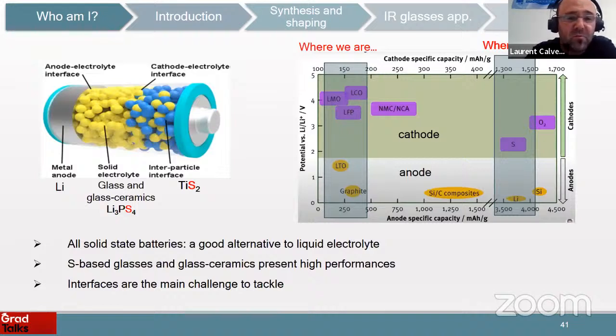So here is an example of what we will be able to do with solid-state batteries. We'll put back the laser pointer. So what will be the next step is to use an anode of lithium and to put some glasses or glass ceramics based on sulfur, so based on chalcogenide elements containing lithium and phosphorus, in the middle of the batteries, and having an interface with other chalcogenide elements like the TiS2 here. So here's the picture to show you where we are with lithium-ion batteries. We are using graphite, and we are using some kind of cathode based on lithium, cobalt, and oxygen. So that's where we are.